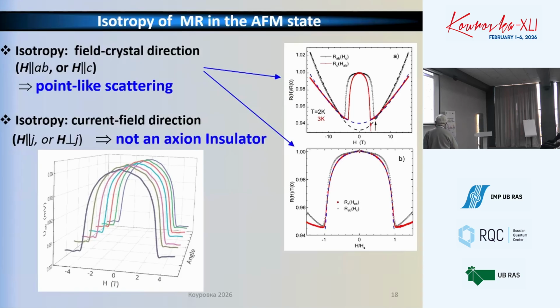Now, to address the remarkable suggestions that this is an axion insulator, we tested the anisotropy. We changed from curve to curve. We rotated the magnetic field relative to the current direction, and we see no anisotropy. So it clearly shows that there is nothing like an axion insulator state. It's not insulating and there are no axions in this material. The next is isotropy. It does not depend on the field direction as you normalize the magnetic field to the magnetization saturation field, and then it becomes direction independent. So the magnetic resistance is isotropic, not only with respect to the direction of current and magnetic field, but also the magnetic field relative to the crystal axis.